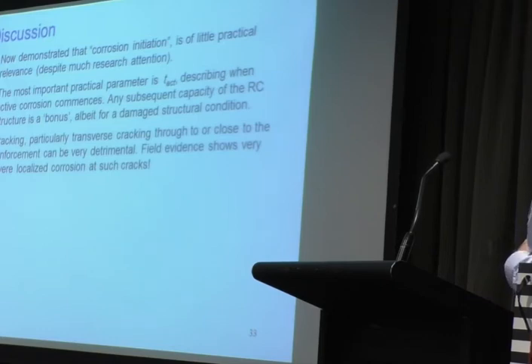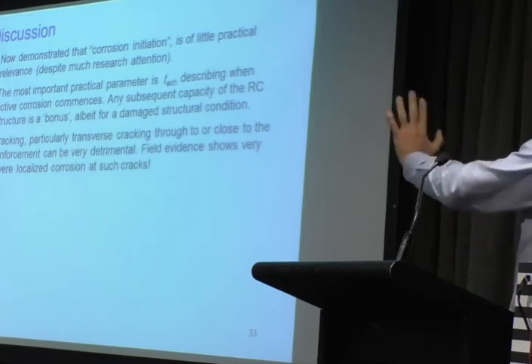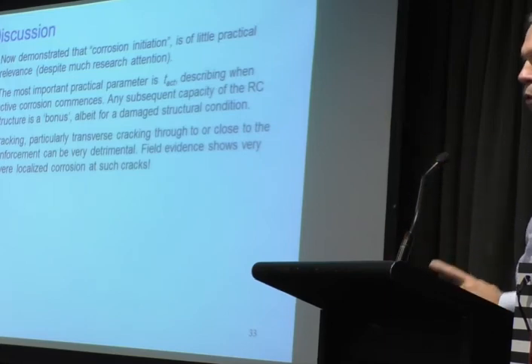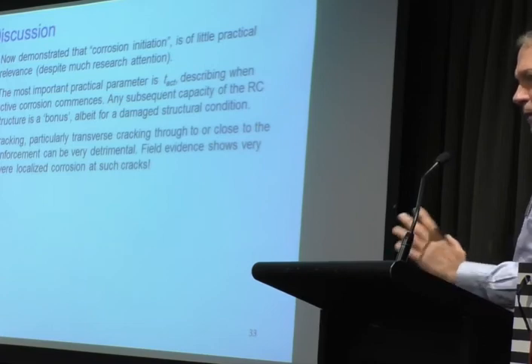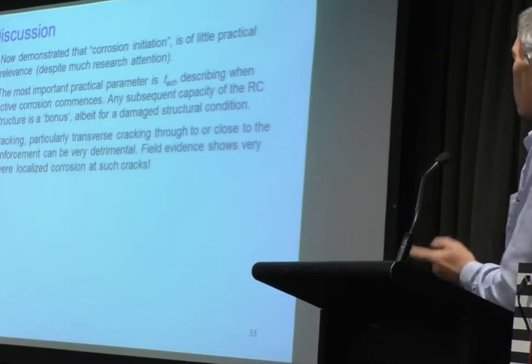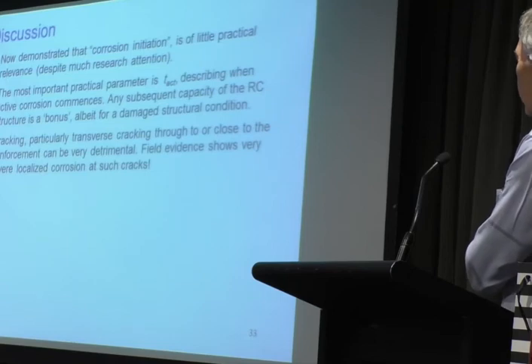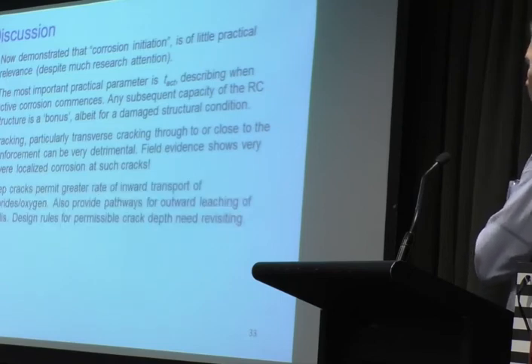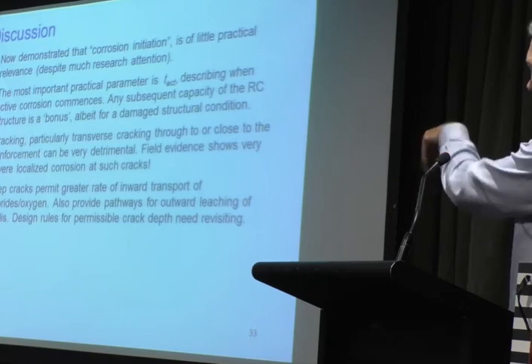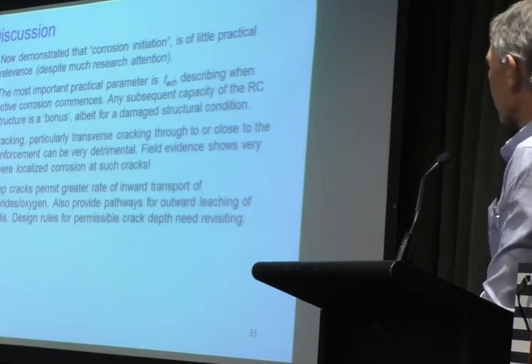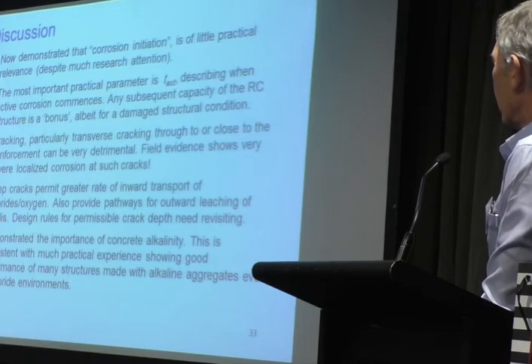Cracking, I've only talked about transverse cracking. I haven't talked about longitudinal cracking because we don't really see that in any of those cases we've talked about unless you've got really poor quality concretes, right? Then you get a different problem. Then the initiation leads to longitudinal cracking if it's a lousy concrete. The deep cracks permit inward transport of, I've just mentioned it, chlorides and oxygen, and out-leaching of alkalis.